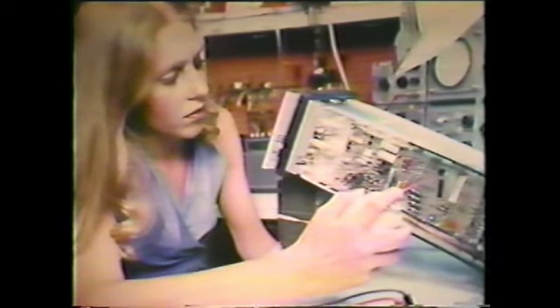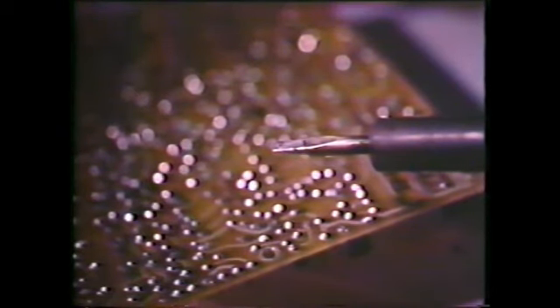Be careful when using circuit coolers. Temperature and static sensitive parts are sometimes damaged by improper use of these coolers. Also, Freon coolers can damage electrolytic capacitors. The most common cause of circuit board damage is excessive heat. Heating a connection too long will melt the bond between the pads or runs and the board. A rule of thumb is never heat a connection longer than 2 seconds. Before applying heat again, allow the connection to cool completely. This allows the pad and board to completely return to a normal state.